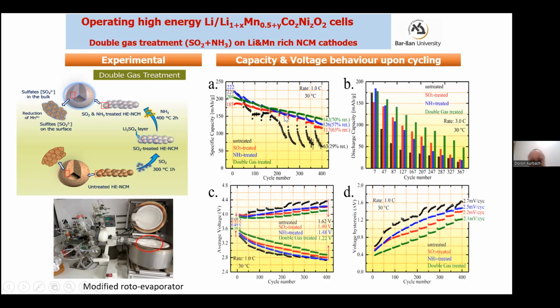And here also again we do experiments at high rate, but also at low rate, and you can see that we have capacity fading of the untreated material. Here you see a comparison by the histograms. So the green histograms demonstrate the discharge capacity during 400 cycles. There is capacity fading, but here the capacity fading with the treated material is much less. And whenever we stabilize the capacity, we stabilize the voltage. Here, this is the voltage stabilization compared to the other samples. This is untreated. This is treated with ammonia, treated with SO2, and this is the double gas treatment, which is effective. So we stabilize the voltage, and also the hysteresis between charge and discharge is lower.